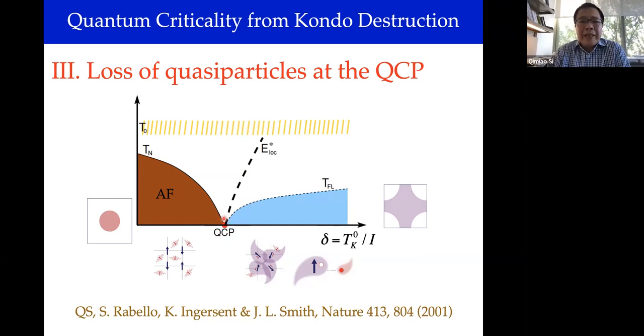There has been effort made by the Wiedemann-Franz ratio measurement, and a particular type of analysis, which I subscribe to, leads to a 10% violation of the extrapolated zero temperature limit of the Wiedemann-Franz ratio, which provides some evidence for the loss of quasi-particles in the case of ytterbium rhodium two silicon two.